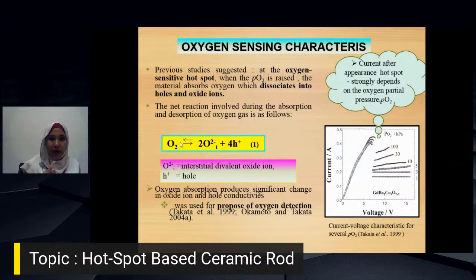So when the hotspot appears and you increase the oxygen concentration in the surroundings, the material will absorb oxygen, which dissociates into holes and oxide ions. You can refer also to this equation. Similarly, when the oxygen concentration is reduced, the material desorbs oxygen and extrudes holes and oxide ions. So the net reaction involves the absorption and desorption of oxygen gas at the hotspot on the sensor rod. Here, the oxygen term refers to the interstitial divalent oxide ion, and h refers to the hole, the hole concentration in the hotspot.